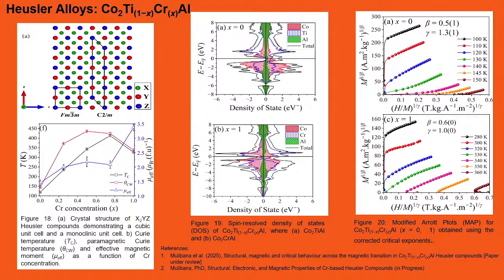On the right, just again, back to quantum critical, we study critical constants, most of our materials, because we really want to understand what's fundamentally going on in the system. What you see on the right here is already a calculation, but this is MH loops. So it's the magnetization as a function of field. And then we extract the initial loop from 0 to maximum field, and then a calculation is done because we're interested in those constants again to see. And we want to drive this so that it almost has linear behavior here. And then we study to get these critical constants out of this.